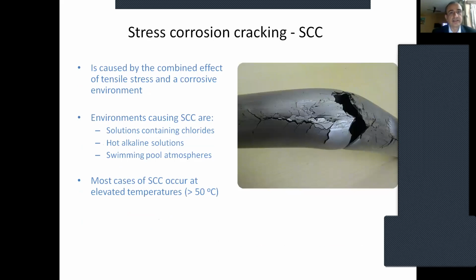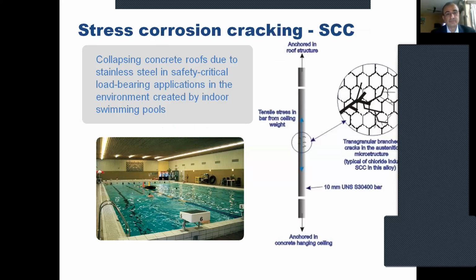This is stress corrosion cracking. Stress corrosion cracking occurs due to elevated temperature and solutions containing chlorides, hot alkaline solution, or swimming pool atmosphere. It is the combined effect of tensile stress and corrosive environment, at elevated temperature as well. This occurred in a swimming pool where the load bearing concrete roofs collapsed due to stainless steel in a safety critical load bearing application in the environment created by an indoor swimming pool, anchoring the roof surface like this. This is stress corrosion cracking.